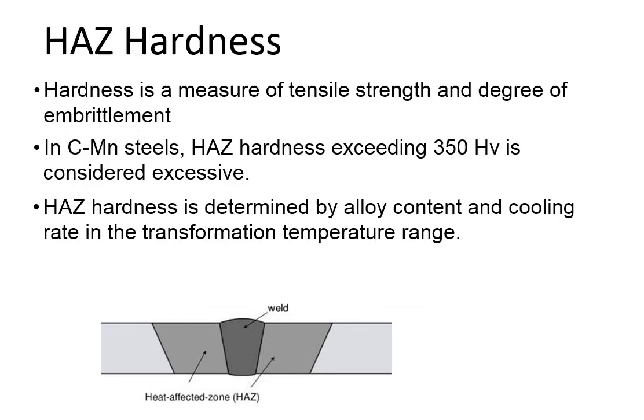HAZ hardness. Hardness is a measure of tensile strength and degree of embrittlement. In carbon manganese steels, HAZ hardness exceeding 350 HV, Vickers hardness, is considered excessive. HAZ hardness is determined by alloy content and cooling rate in the transformation temperature range.